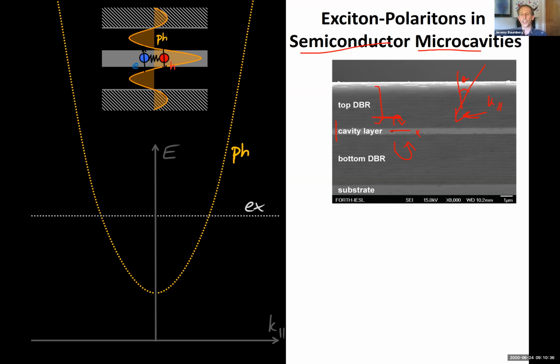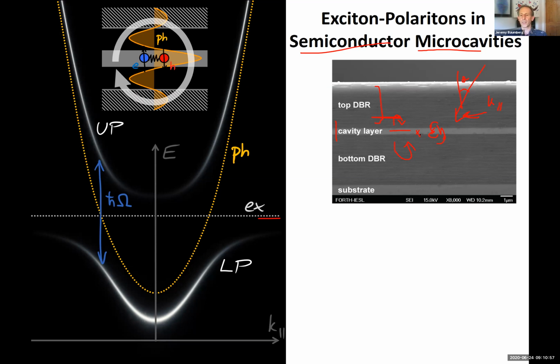And then what we would do is grow a very thin quantum well, which had an electronic excitation, an electron hole pair, which oscillate around each other. So there's like a hydrogenic atom, but for semiconductors, and we could tune this to different energies here. And the trick was to build the system so that when you grew it, you got strong coupling. Essentially the electron hole pair, the exciton, would recombine and emit a photon. That photon would rattle around the optical cavity before being reabsorbed in the exciton, and then be re-emitted and reabsorbed many, many times before it escaped through this mirror here. So what you got was this strong coupling, this splitting between the two branches where they crossed.